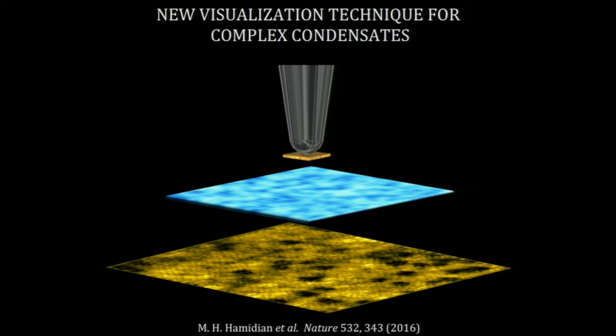You are not able to tunnel, or it's not clear, right? So theoretically, you shouldn't be able to tunnel into that. But whether you can tunnel in and then the Cooper pairs reform somehow, or in the case of the experiments where you have slight distortions of the unit cell, that allows you to have a slight S-wave component on top of your D component. Could this be a measurement to measure the order parameter of pnictides or something? Yes, definitely, right. So if you take a D-wave tip and then put it on a pnictide, yes.